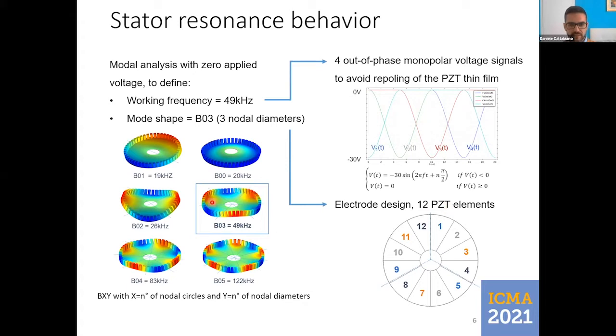Since the mode is 3, we divided the 12 electrodes into 4 groups of 3 electrodes. In this case, electrodes number 1, 5, and 9 are actuated and controlled together, and so for 2, 6, and 10, and so on. For each one of these channels from 1 to 4, we applied a monopolar sinusoidal voltage from 0 to minus 30 volt in order to keep the poling of the piezoelectric material.